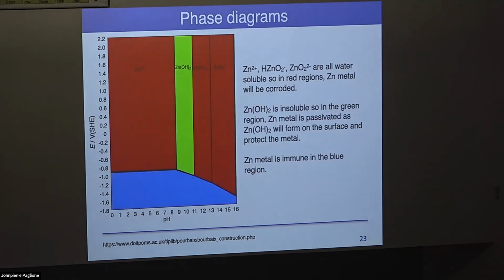But again, all these Pourbaix diagrams for all the elements are computed and tabulated in different handbooks. Importantly, what you might see in literature, especially in the geochemical literature, is this distinction between immunity and corrosion. For zinc, all these red regions are where the species considered, for example Zn2+ or HZnO2-, is soluble in water. So all these red regions are areas where you might see the term corrosion. If you put zinc into water at these different regions, your zinc will start to be corroded and dissolved in solution.